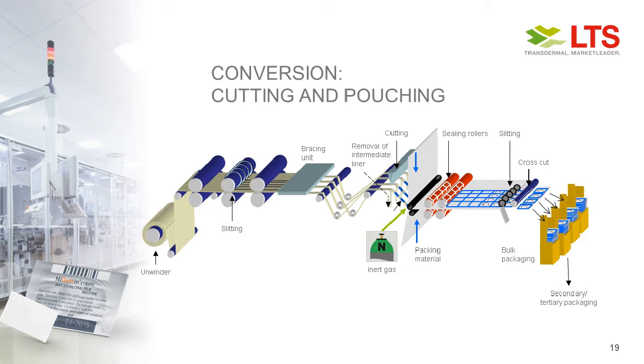The last step is the conversion step, and as you can see here, a picture on the left side of a conversion line where the narrow roll is placed from the slitting machine. Here we can see that the narrow roll is further slit into small stripes, and from these small stripes, the OTFs are cut out in their dimensions along the processing direction. Then they're transferred into the packaging material, potentially also filled with inert gas, where they are individually sealed, and we end up with a sachet, a primary package pouch, like you see on the bottom left of this slide. There's a single film and a single pouch being packaged. And commercially, I would say this is the main packaging design seen for all OTFs.